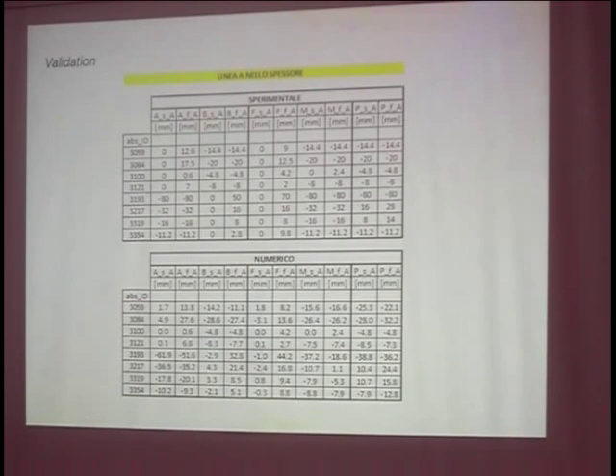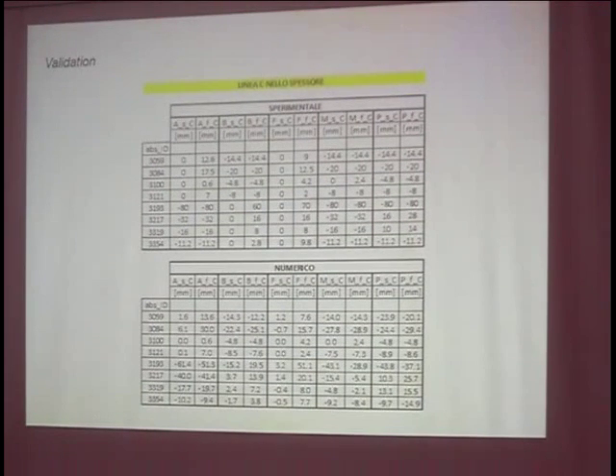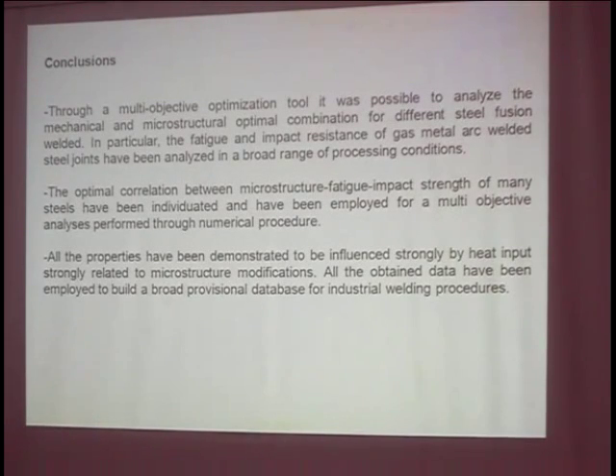For the microstructural evolution, the system doesn't work so well in terms of prediction of the evolution. This means that just for this kind of work, the system needs much more experimental data to be trained in order to be more precise on the final evolution of the microstructure, because it's very complex: martensite, austenite, pearlite, and mixing of 2 or more microstructures, and so it becomes very difficult.